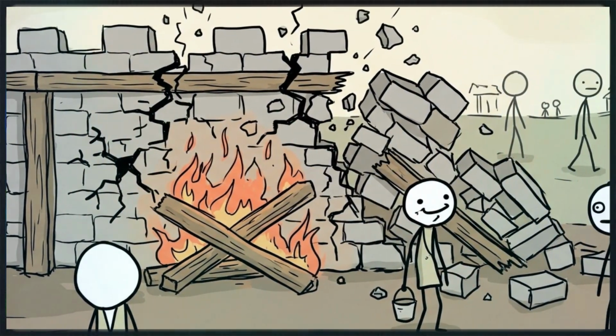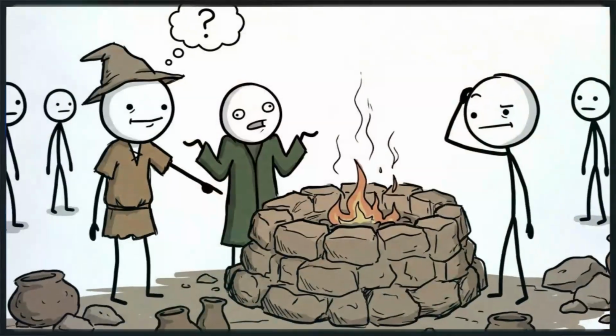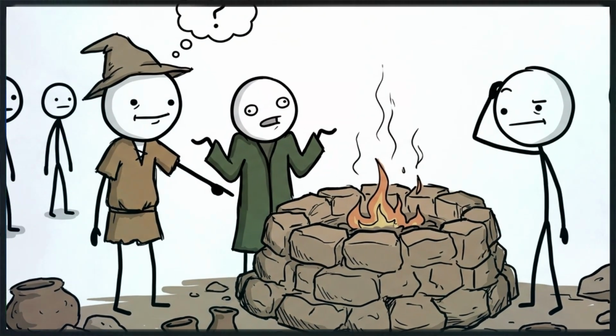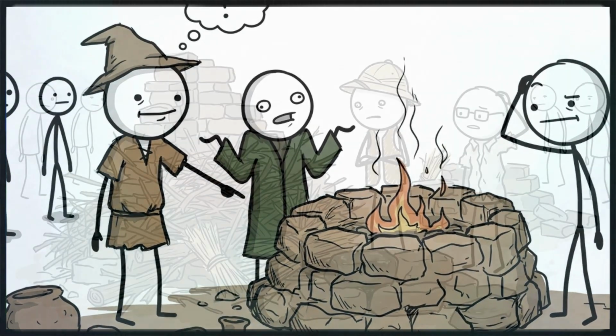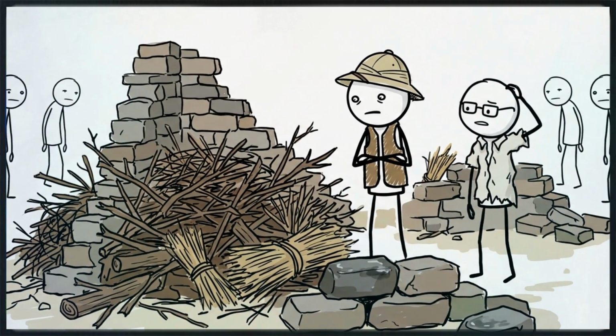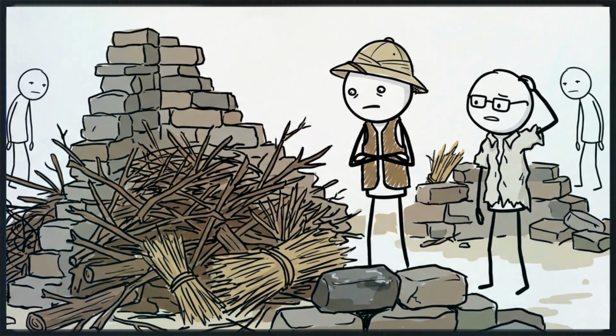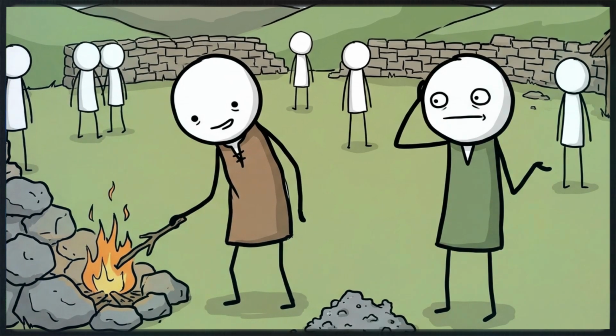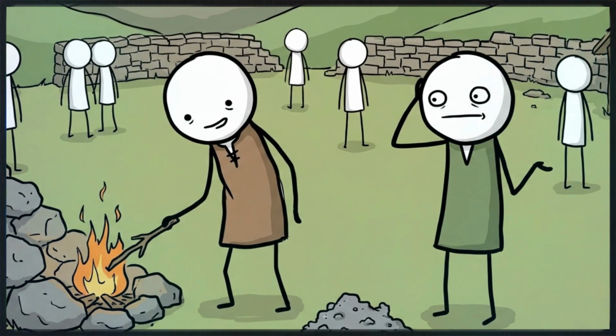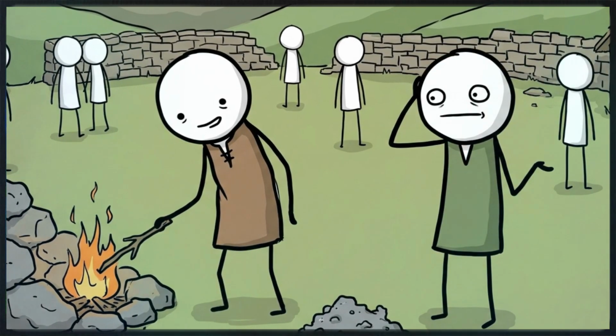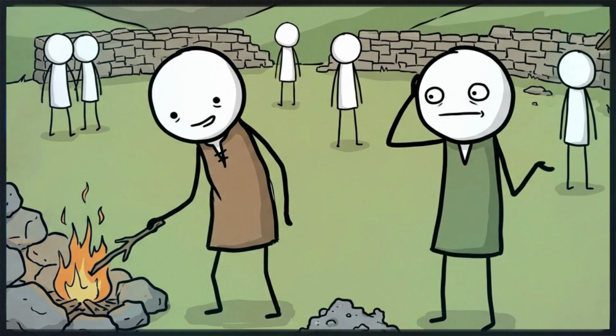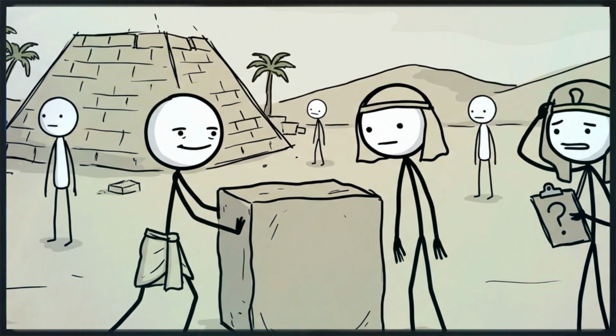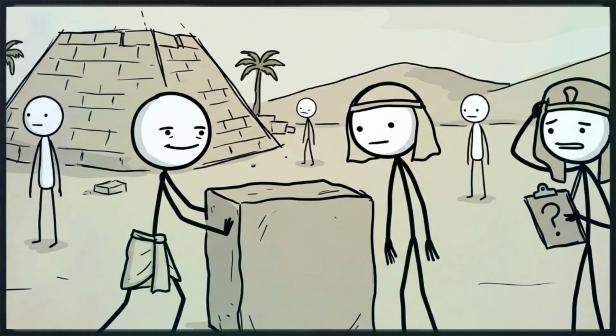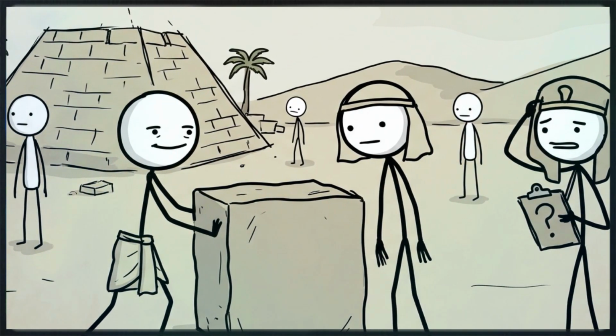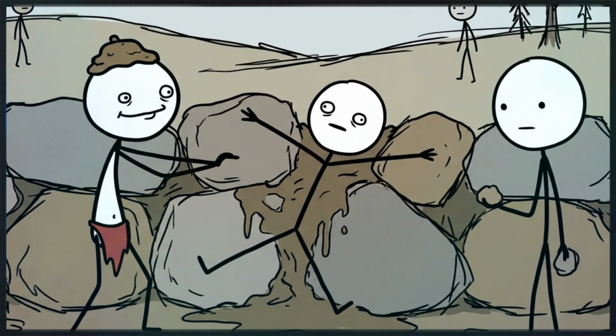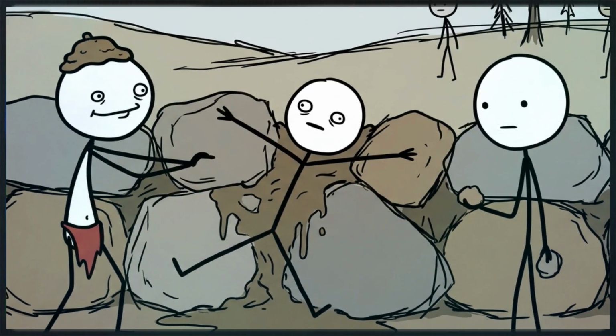The results were universally disappointing. The burning timber caused the stones to violently crack and the walls to collapse due to rapid kinetic expansion, but the fires completely failed to reach the sustained critical mass required for true vitrification. At best, after packing the ruins with absurd amounts of extra brush and fuel, the researchers achieved microscopic, superficial surface glazing on a few select stones. They produced absolutely nothing resembling the monolithic flowing rivers of glass found at ancient sites like Tap o' Noth or Craig Phadrig.